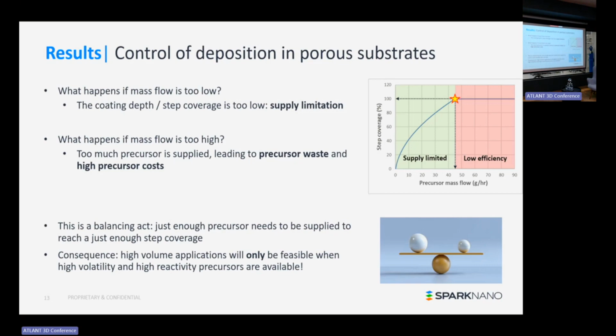Consequence of all this is that high volume applications like the battery example I mentioned will only be feasible if you can use high volatility and high reactivity precursors. So choice and selection, development of precursors is very, very important. If you come up with really exotic, low reactivity, low stability precursors that can only be synthesized by a PhD student somewhere in a fume hood, even if the battery performance is excellent, it will never ever be scalable. It's just not possible.